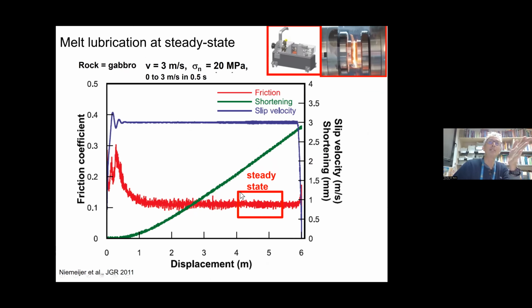Then we move toward the steady state, or what we call the steady state, but once this critical initial weakening has been overcome somehow, there's a sort of threshold. The friction is still quite low. As you have seen in the movie, it's about 0.3. You start from a rock where the friction is at 0.7, okay? There is this thing happening, and then there is this evolution. We can discuss this, what we call steady state.